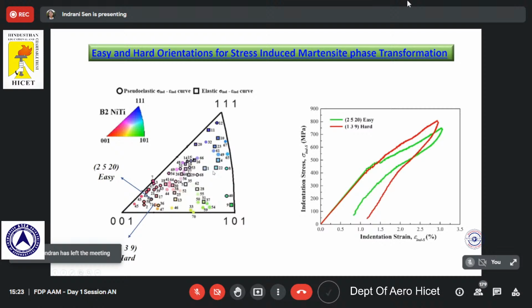As I said, different orientations may also undergo the transformation based on different CVPs. So this is very important if you are talking about fabricating a single crystal, let's say, sensors. We would like it to have the best pseudoelasticity, and we cannot ensure that unless we know which one is actually supposed to give us the best pseudoelasticity and which orientation is not suitable for pseudoelastic recovery.